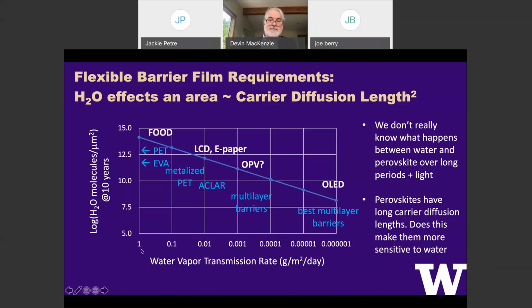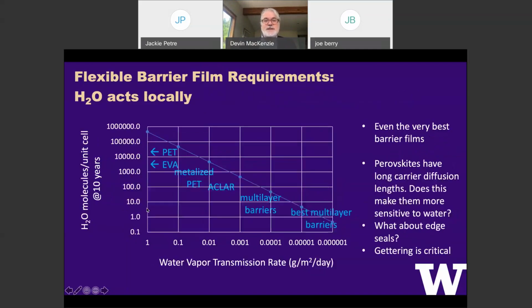We're talking about even the multi-layer barrier films, kind of world-class multi-layer inorganic-organic stacks on plastic, on polyester. Even there, we're talking about 10 to the 7, 10 to the 8 H2O molecules per micron squared after 10 years if you don't do other things. Very, very tricky. If we take the more optimistic viewpoint that H2O degradation is only going to act locally,